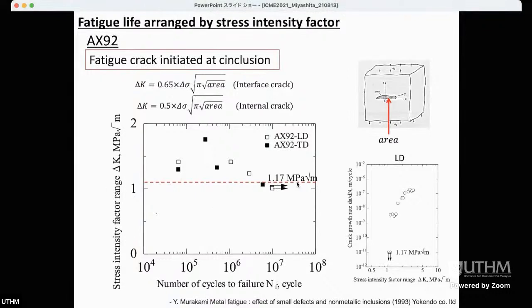And this dashed line is showing the threshold value. Below this line, specimens were not broken at 10^7 cycles. And fatigue strength data were arranged by the stress intensity factor, as you can see from this figure. That means the fracture mechanics approach is quite effective to understand the fatigue characteristics of this kind of alloy.